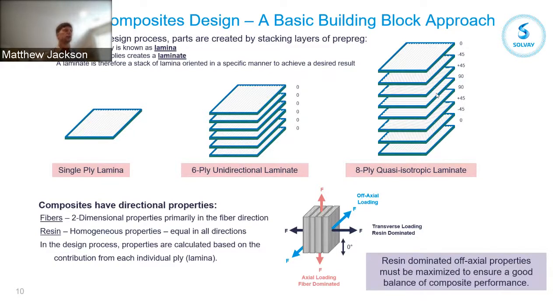And so if you look at the orientation of the plies on the right-hand image, we go from 0, minus 45, plus 45 to 90, and then a 90, plus 45, minus 45, and 0. And so we do have a mirror plane in the middle. And that's to try to create as balanced a layup as possible and to maximize the performance in every direction. So again, the fibers give us strength really in one direction, and we try to balance that out by creating these quasi-isotropic laminates, which then gives us multiple.